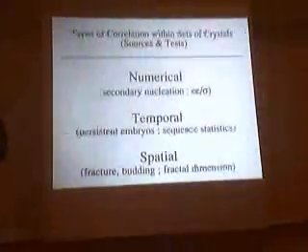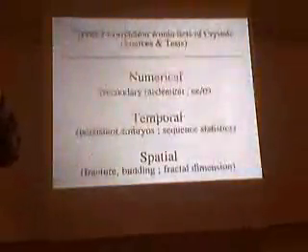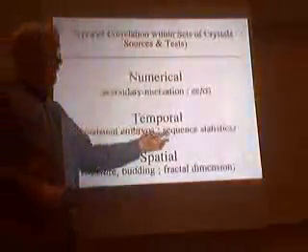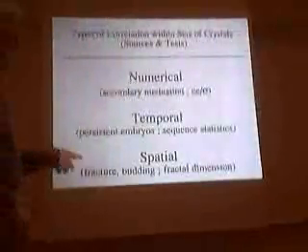Then there can be temporal correlation. You take a flask, do the crystallization, heat it to dissolve it again, do the crystallization again, and again. See whether the right and left-handed outcomes are random. If there were persistent embryos that you never destroy, even by heating a great deal, then it's conceivable you'll come back to the same hand. So you can test that by sequence statistics to see whether the sequence of right and left is random or deterministic.